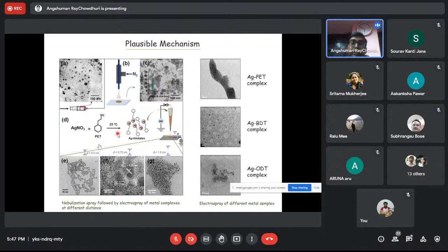Like this, the materials produce silver thiolates inside the droplet, and these silver thiolates mean there is silver ion and thiolate, Ag+ and thiolate. When these silver thiolates are depositing, they get electrons from the substrate and produce silver nanoparticles. In that way, the monodispersed particles are forming. So the polydispersed particles produce transient precursor species as silver thiolates, and they again reorganize to form the monodispersed particles.